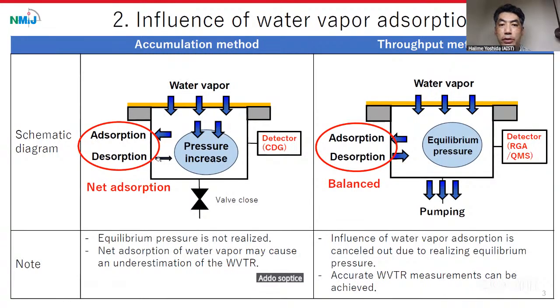Adsorption is different between the two methods. In the case of the throughput method, on the right-hand side, pressure equilibrium is realized, which means the adsorption rate onto the vacuum chamber is balanced with the desorption rate from the vacuum chamber, which means the net adsorption rate becomes zero. In other words, the influence of water vapor adsorption is cancelled out due to realizing equilibrium pressure. Therefore, accurate WVTR measurements can be achieved.